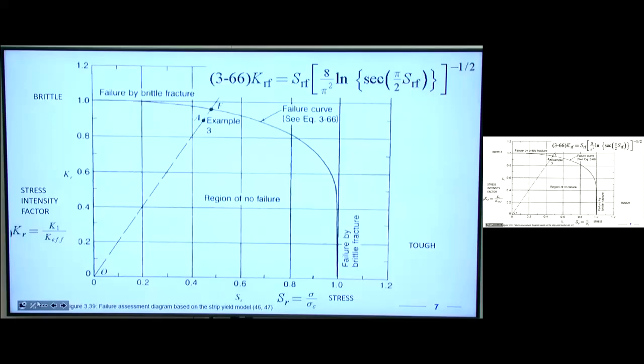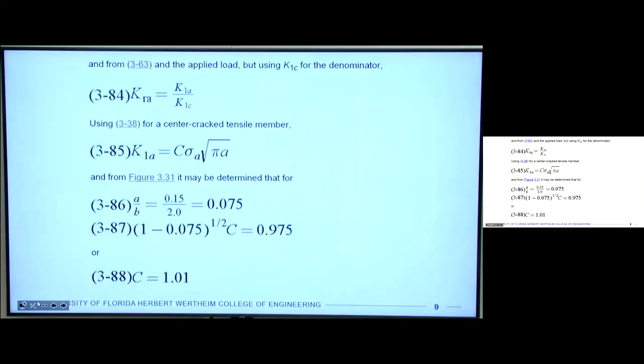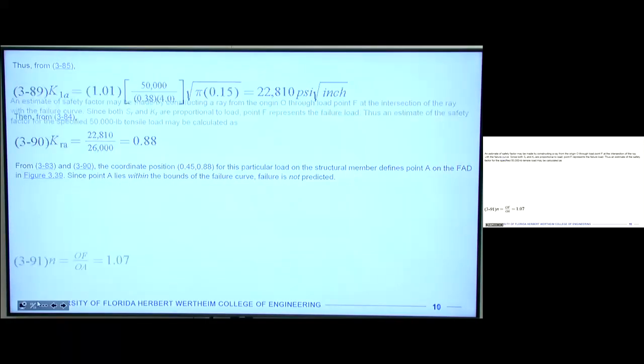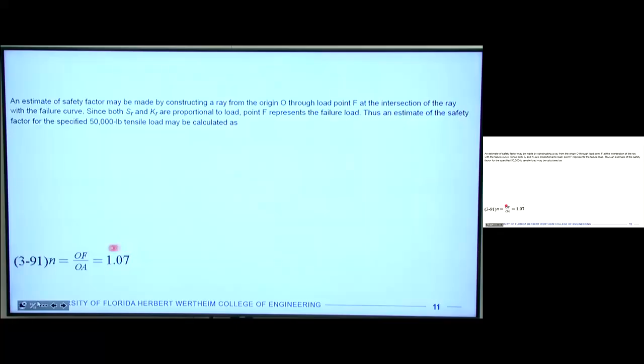And if we do that in this case, we get a value of 1.07. So it's just these two vectors that they drew on the plot there. And so we don't really have a very high safety factor. So if we go much above this 50,000 pound tensile load, then we would expect to get a crack propagation and brittle failure. Question?